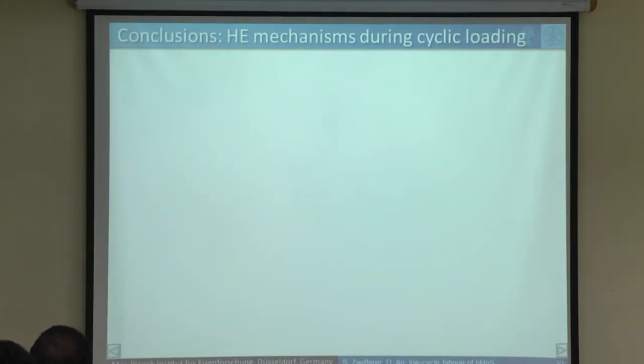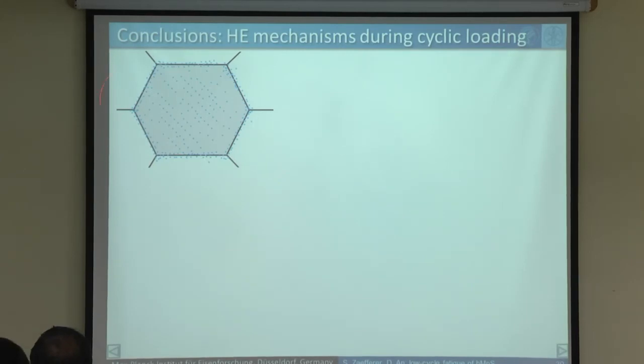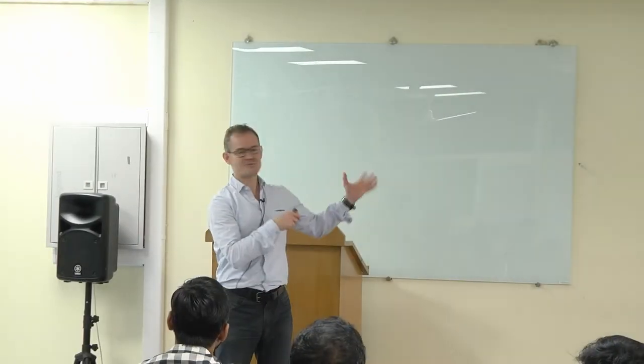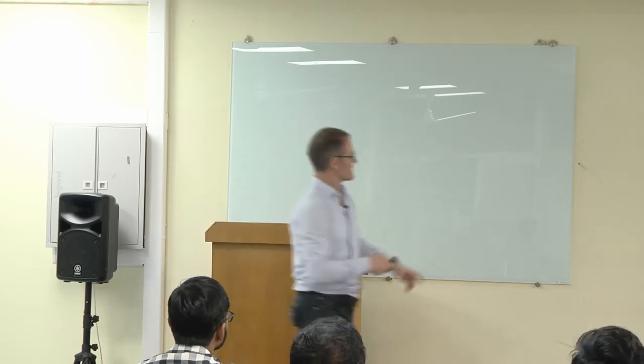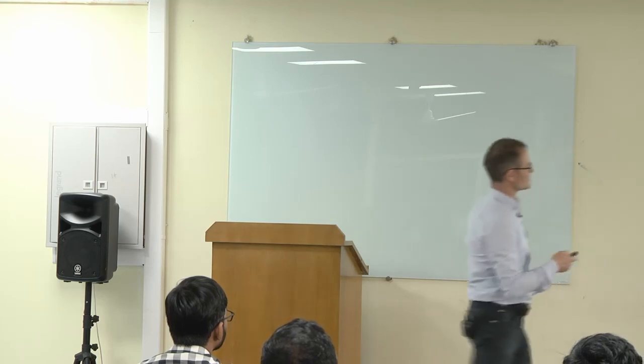So, hydrogen embrittlement mechanism during cyclic loading of these, actually, it was manganese steels. I forgot to mention that, but it's important. So first we have hydrogen inside. Hydrogen concentrates on the grain boundaries. This is our current work, to prove with atom probe that the hydrogen is really where we claim it. We have only indirect proofs, and now Hina Kanchandani has the unfortunate PhD thesis theme to show where the hydrogen really is. So in the beginning, it's on the grain boundaries, but also everywhere in the volume.